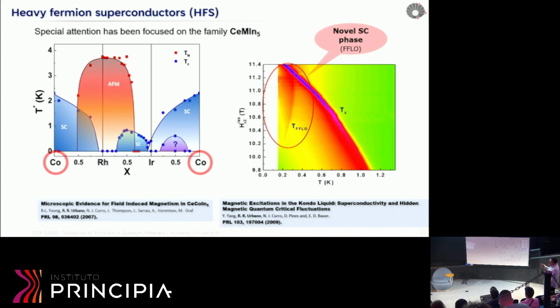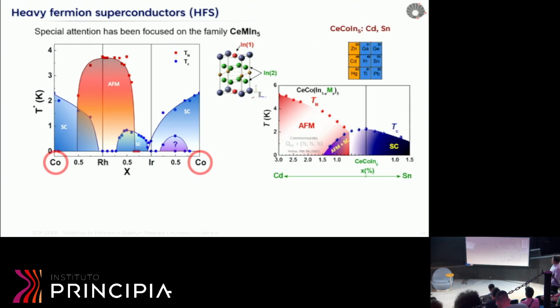But what we found here was a very inhomogeneous state or phase with field-induced magnetism. About FFLO, I don't know, we couldn't say much. Some people still claim the existence of this over there. Some people just don't believe there is something related to that. However, when we pick the samples here with a superconducting ground state and dope it, what happens is represented here in this phase diagram.